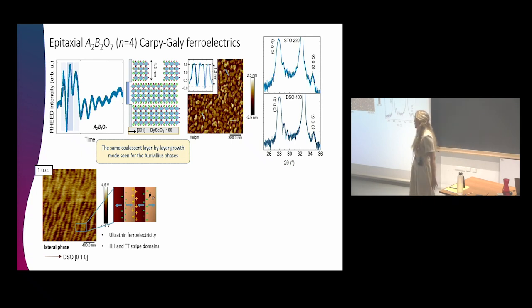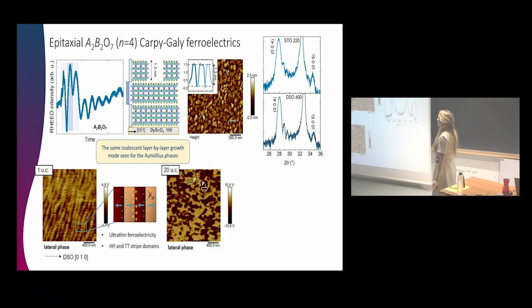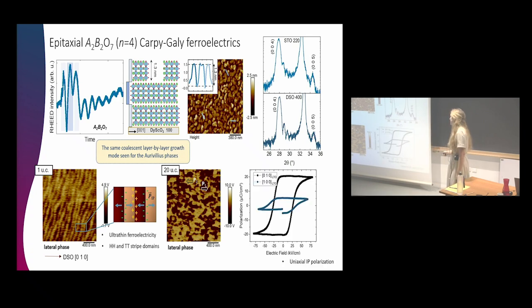Of course, when you grow thicker films, we have, again, uniaxial in-plane polarization with 2 ferroelectric components, and we can actually switch quite nicely in the P loops in the plane with some interdigitated electrodes to show that, okay, we have one clear in-plane polarization axis that's preferred. And interestingly, it's even 4 times higher polarization than whatever was reported in the bulk. So the fact that we're trying to grow these films epitaxially high quality is really improving the properties and also increasing the TC hand in hand.